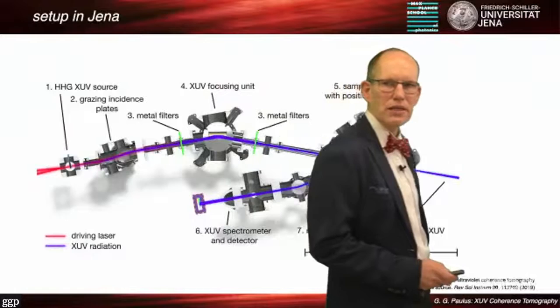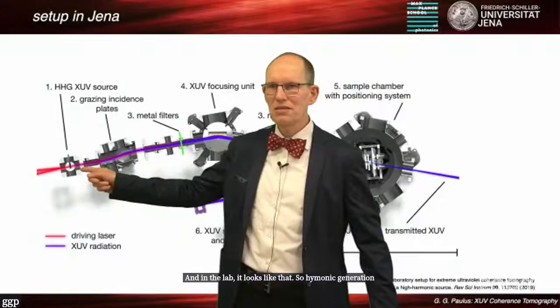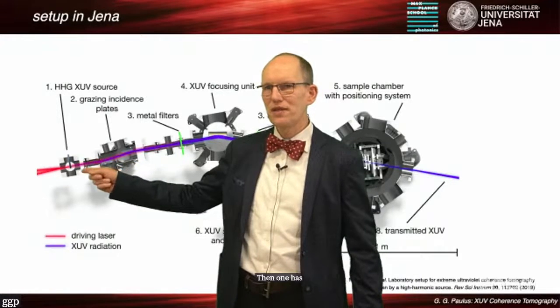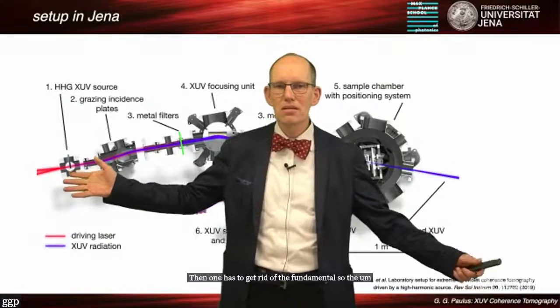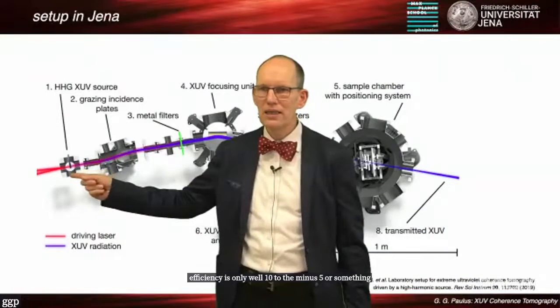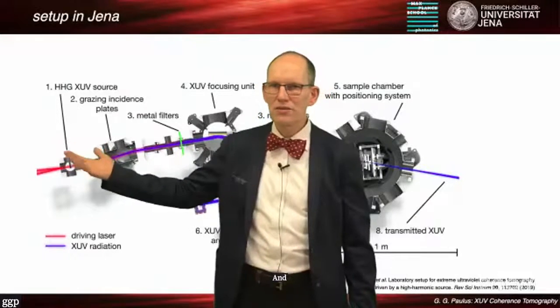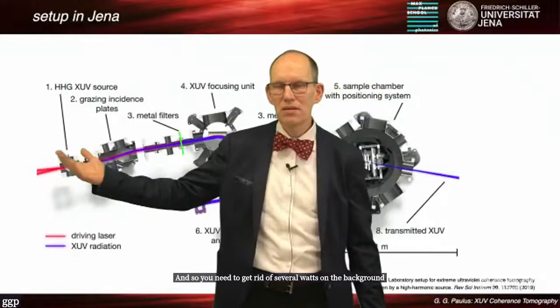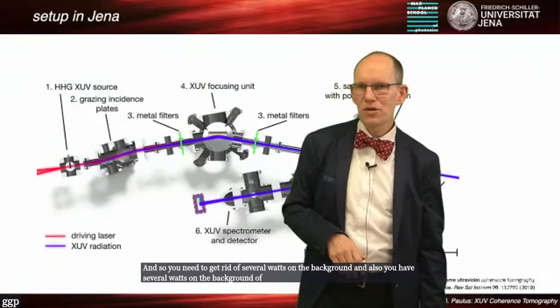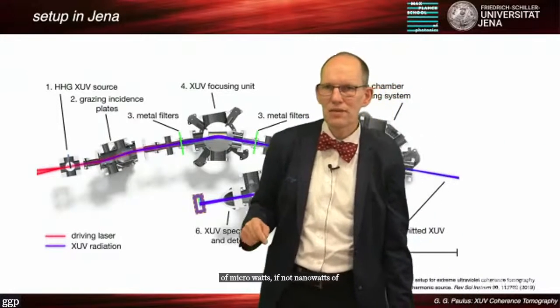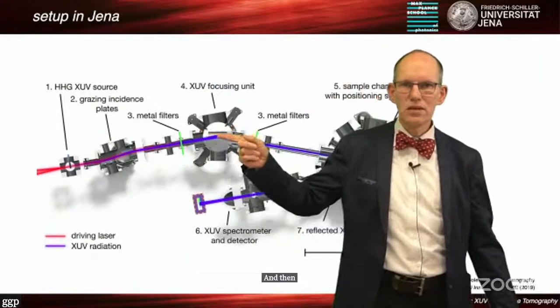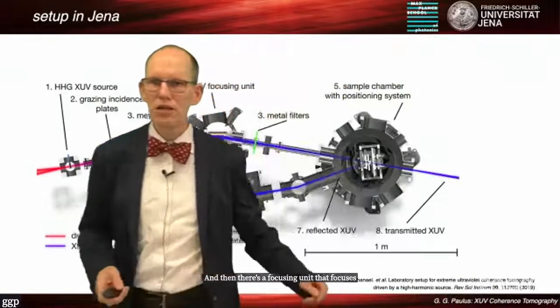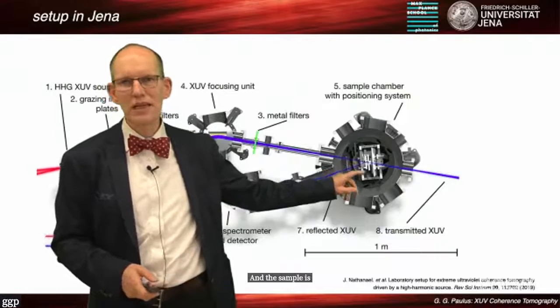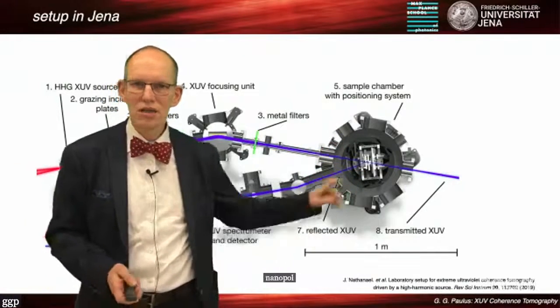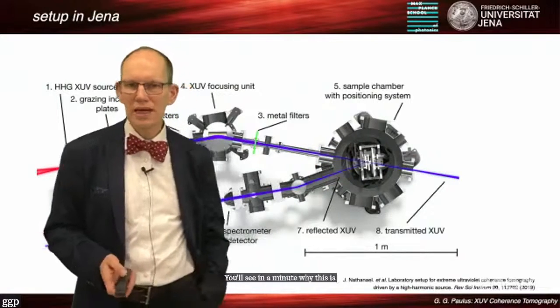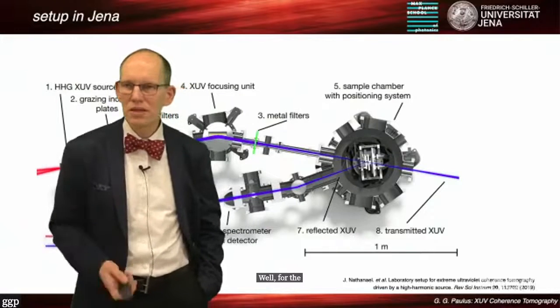And in the lab, it looks like that. High harmonic generation is the smallest part. Then one has to get rid of the fundamental. The efficiency is only about 10 to the -5 in our case. So you need to get rid of several watts of background to see microwatts, if not nanowatts, of the XUV radiation. Then there's a focusing unit that focuses the XUV radiation on a sample, and the sample is situated on a sophisticated nano positioning stage. You'll see in a minute why this is so sophisticated.